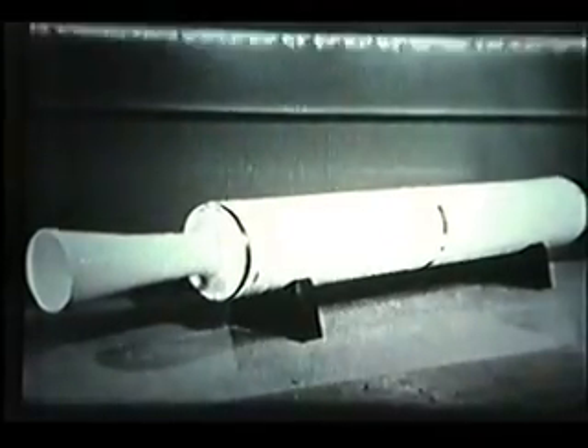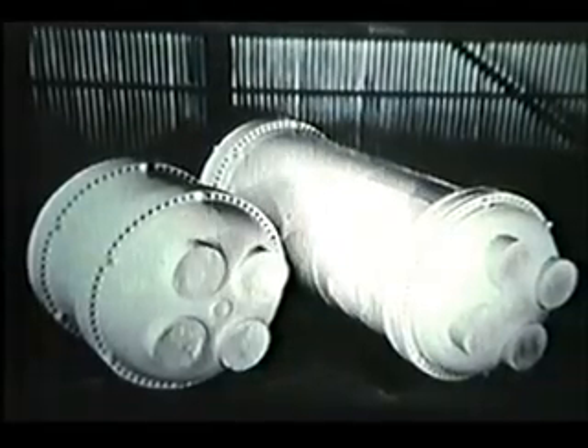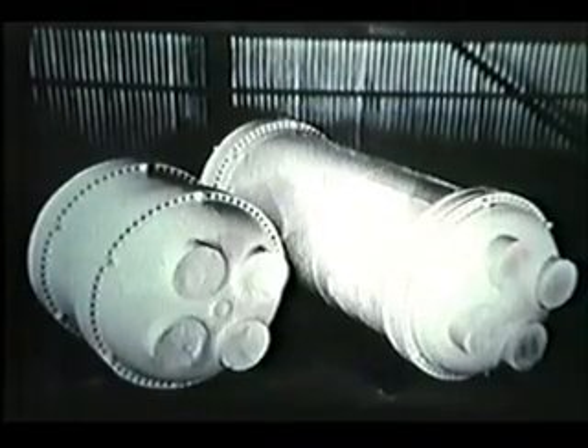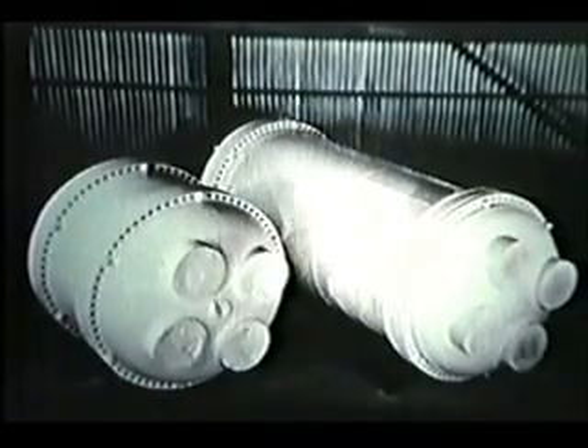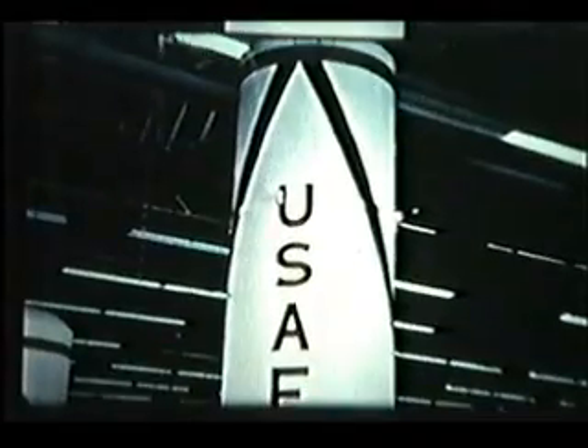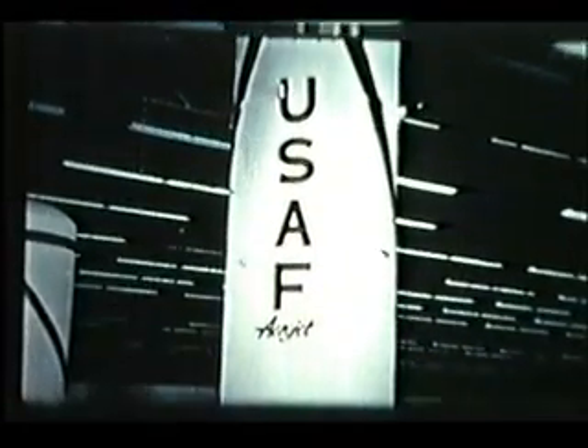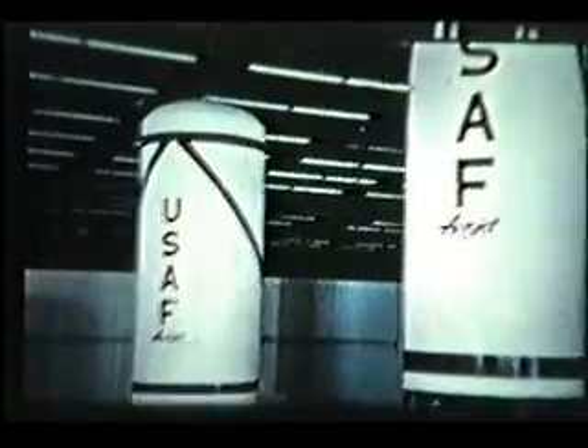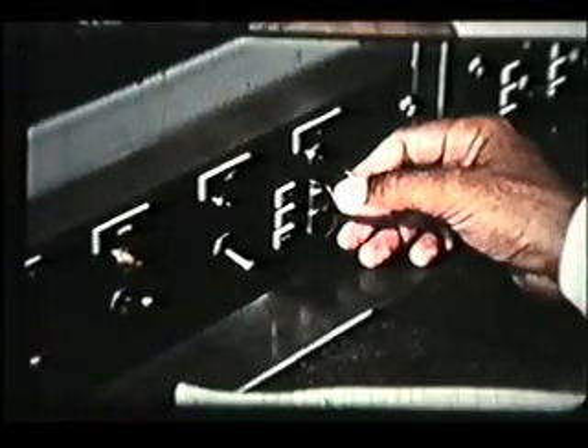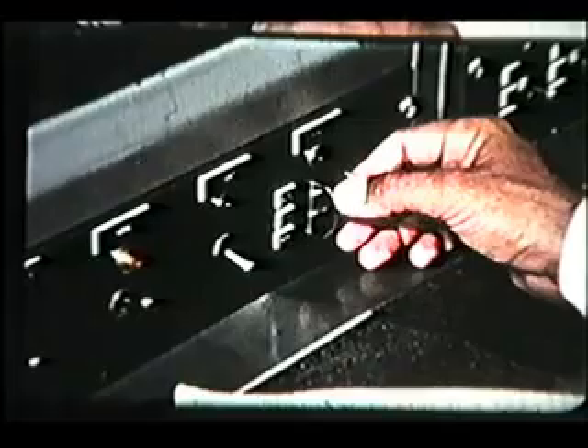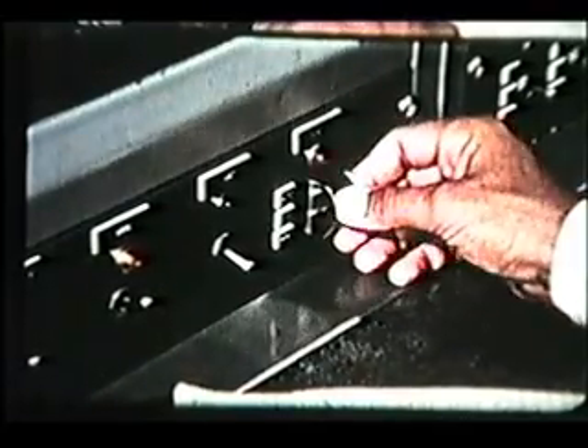These include the Hawk, the Sparrow, the Bullpup, the Tartar, and here shown the Polaris, and the succeeding Minuteman scene. All are being assisted by the use of Rokide on nozzles. A view of the static test of the Polaris engines shows solid fuel gases at over 5,000 degrees F. The erosive forces and corrosive action of these fuels is increasing as temperatures in the 7,000 degree range are considered and tested.